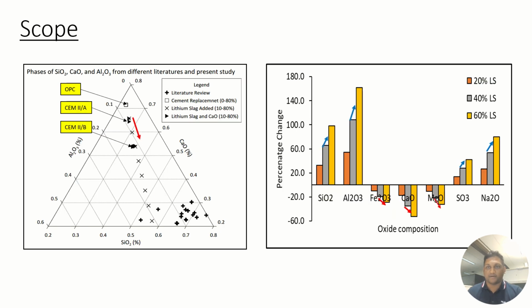Most researchers have found that 10 to 20% cement replacement by lithium slag is feasible. This study was challenging as high volume supplementary cementitious material increases the unknown phases, specifically lithium slag increases the sulfoaluminate phases. Earlier, pozzolanic activity was calculated from oxide composition and strength activity index only. The previous studies left an opportunity to focus on chemical tests to assess the lithium slag pozzolanic activity and hydration products.